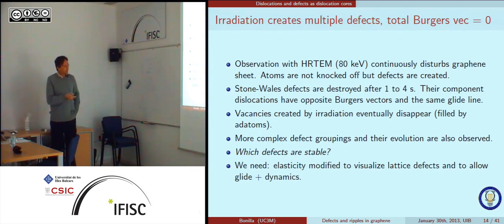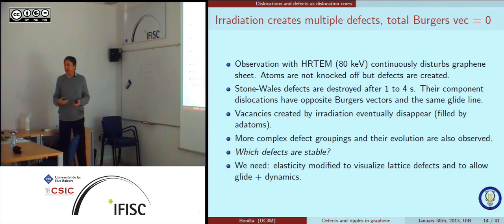this is what the experimentalists see. Okay, this low voltage electron microscope disturbs the graphene sheet so that you rotate bonds and create these Stone-Wales defects that are destroyed. We interpret that as, okay, they should be destroyed because they just share the same gliding line. The lattice is really disturbed all the time because you are irradiating the sheet. That means that the electrons are transmitting some energy to the atoms, and sometimes this is enough to overcome energy barriers that keep them from moving, and that is what plays the same role as these external forces that I put in the simulations. The vacancies disappear, filled by atoms.